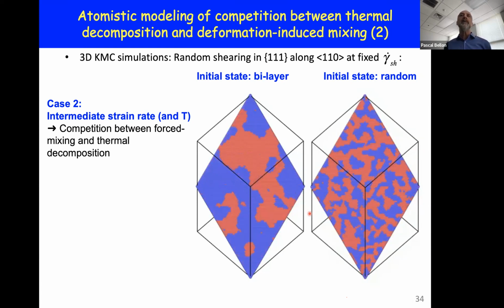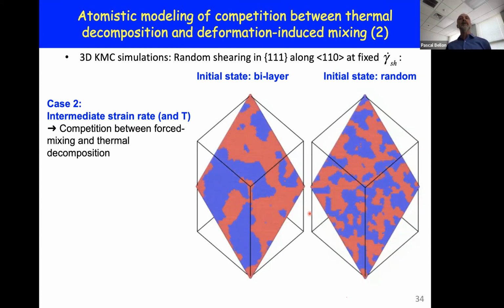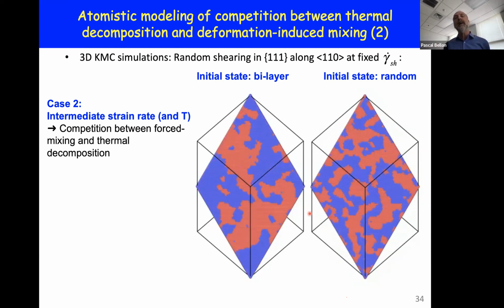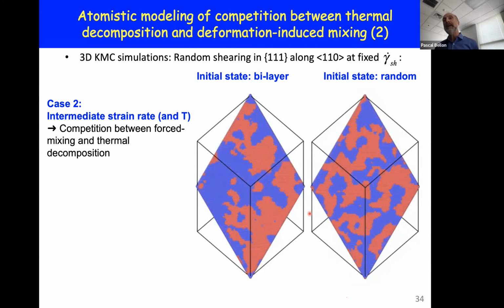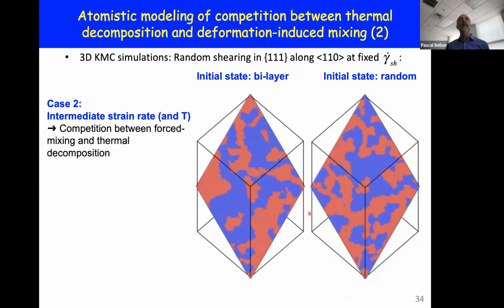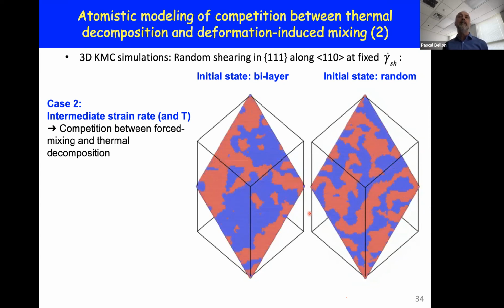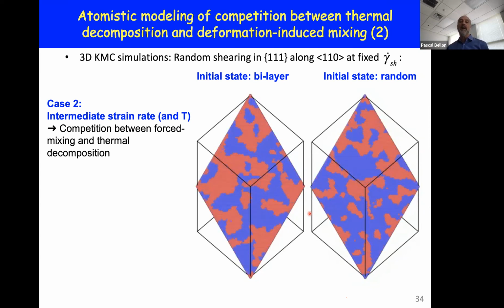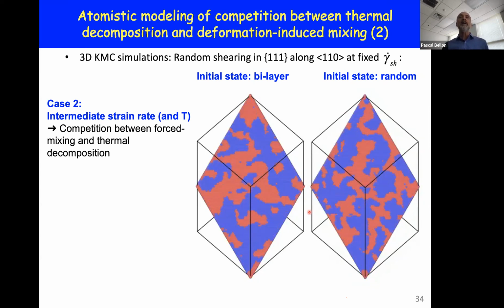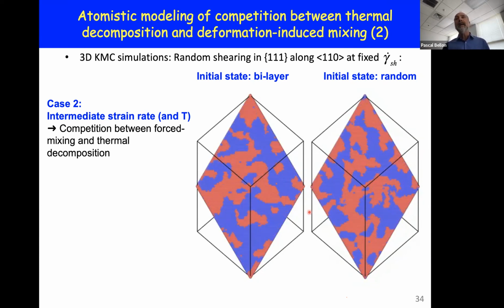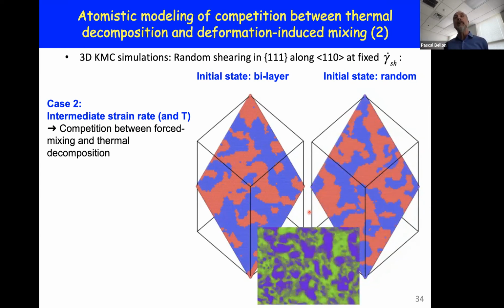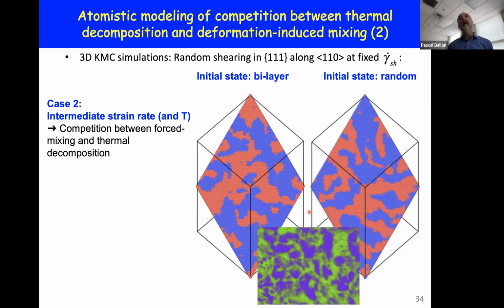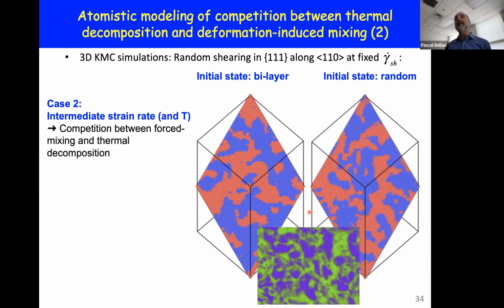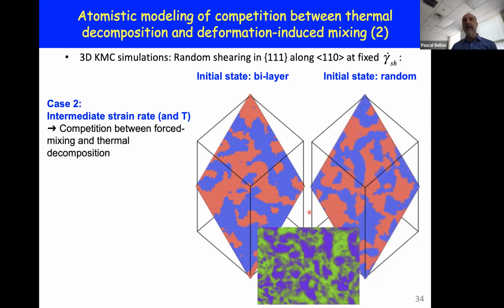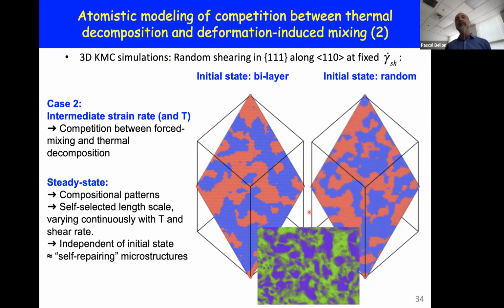If we were to start with the solid solution on the right, now this structure coarsens. But what's intriguing is that if you let them evolve long enough, they will essentially reach the same steady state, that is, a microstructure or two microstructures that are statistically equivalent. We think that this captures very well what I showed you on the ball milling, where you can see, after zooming at a certain scale, the coexistence of copper-rich and silver-rich regions. And so here we have a self-organization or patterning under plastic deformation.